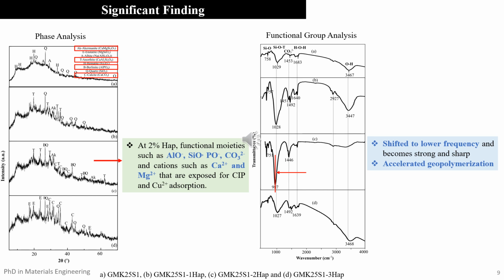Now let's look into the result and discussions. Based on the phase analysis, in addition to analcime and anorthite, additionally berlinite and calcite was formed with the incorporation of 2% of hydroxyapatite. Thus, at 2% of hydroxyapatite, the functional moieties such as alumina, silica, phosphate, carbonate, and cations such as calcium and magnesium that are exposed for ciprofloxacin and copper adsorption increase.